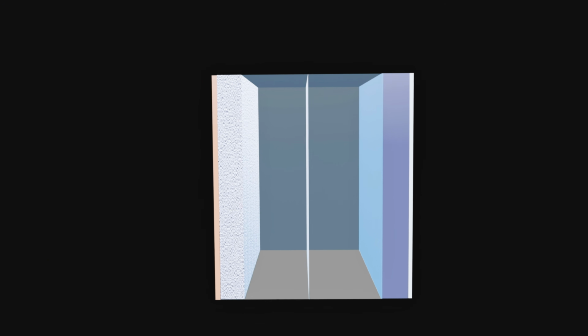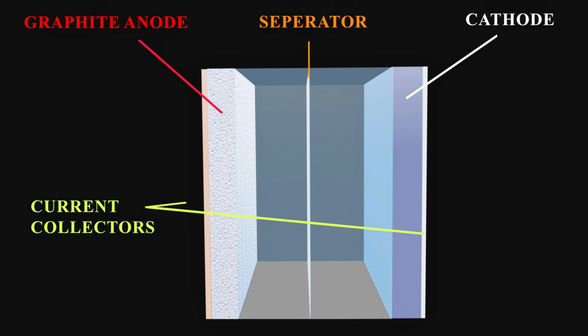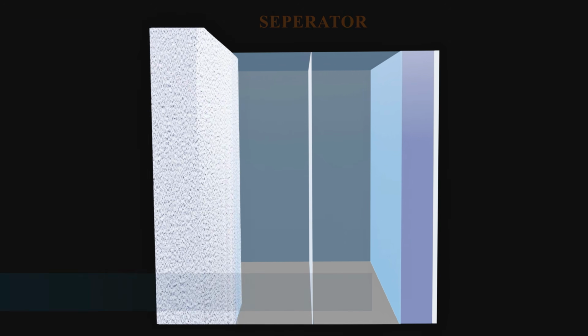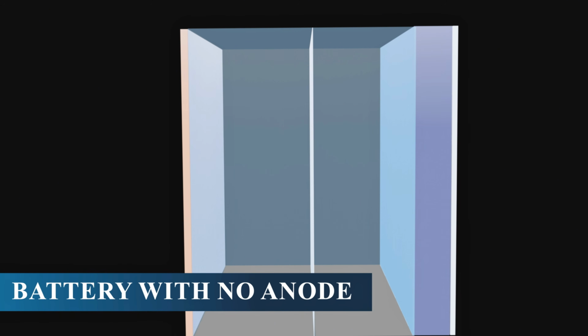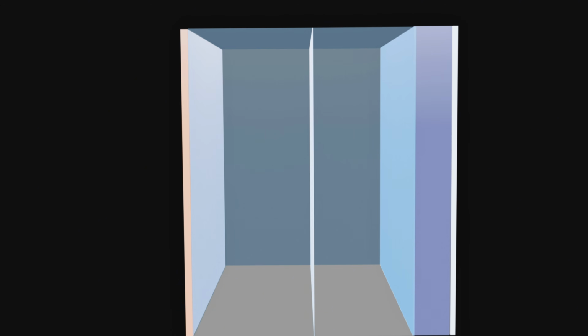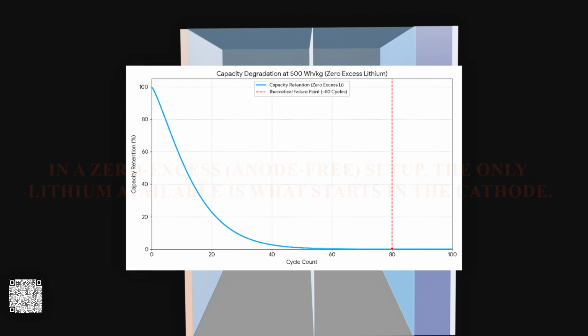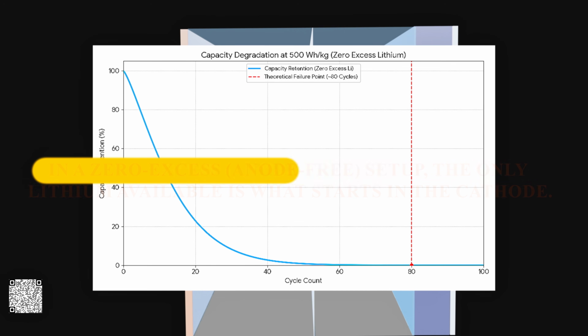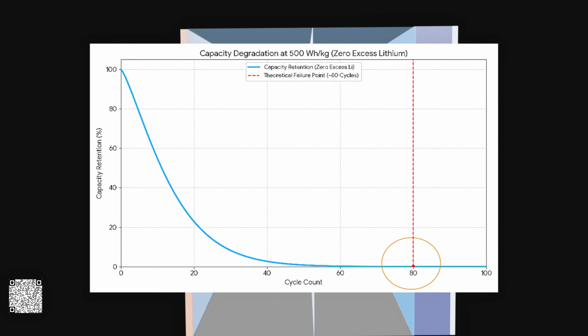We've spent decades trying to kill the graphite anode because it's dead weight, but when you strip it away, you're left with a battery that has no place to put its ions. To hit 500 watt-hours per kilogram, you have to operate with zero excess lithium, which usually means the battery eats itself in fewer than 80 cycles.